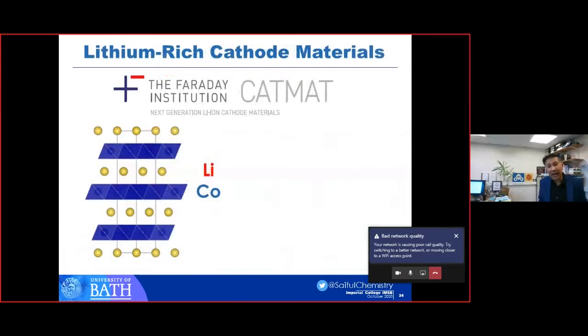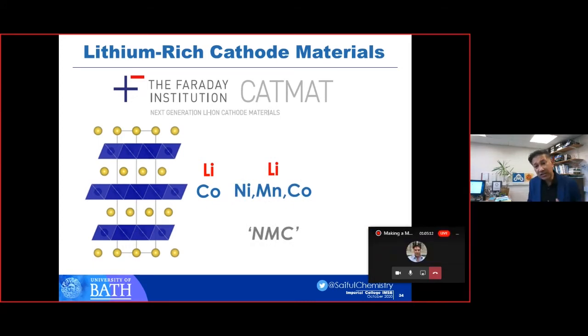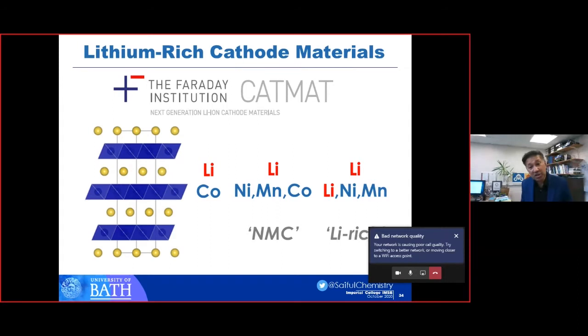And one of the areas that we're looking at is, can we replace the lithium cobalt layered oxide? The next generation is what are called NMC materials, replacing the cobalt by nickel and manganese and reducing the amount of cobalt but increasing the amount of nickel. And then to increase the energy density, how much lithium you can store, how much energy you can store, there are lithium-rich NMC. However, they pose problems in terms of voltage fade and voltage hysteresis. So we're trying to understand these materials much better to try and mitigate the problems in these lithium-rich high energy density cathode materials. So that's one of the aspects of our work.